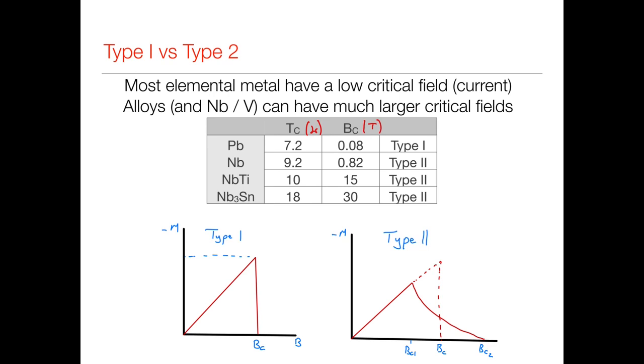Some of the highest fields we have come from something like niobium and tin, both good superconducting elements. When we alloy them together, we get a reasonably high Tc, and the critical field is now 30 Tesla. So this is starting to be technologically useful for producing magnetic fields for NMR or MRI machines. And it turns out that there is a critical difference between these elemental metals and, well, just a small number of the elements, niobium and vanadium, but typically the alloyed materials, which have a very different magnetic behavior.